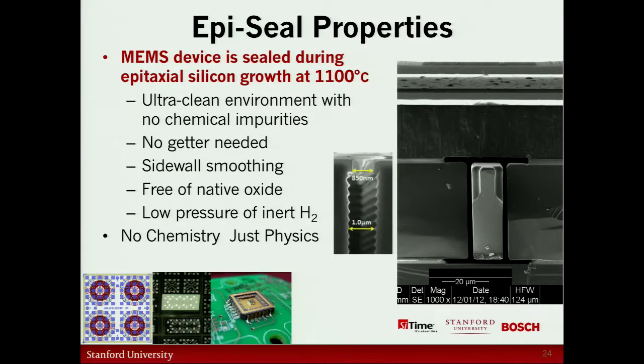There's no native oxide here. There's no oxygen, because during that high temperature seal, basically the silicon acts like a getter for anything like oxygen during the sealing process. And all that's left over is a low pressure of inert hydrogen, which is basically an ideal gas. It doesn't stick to anything, it doesn't react with anything. If there's a little bit of it bouncing around, that's perfectly fine. It's not going to do anything that would change the properties of the device.